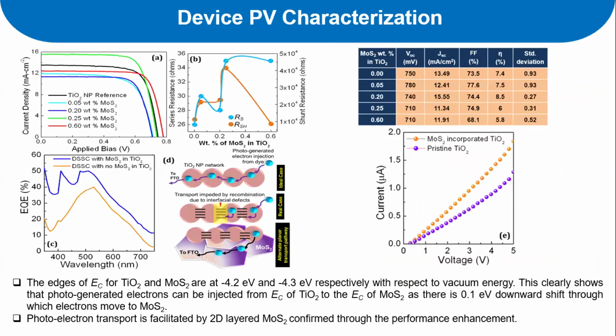Once we have that photoanode, then we go for the device fabrication, the excitonic photovoltaic device fabrication and characteristics. The first figure, A, shows the current-voltage IV characteristics obtained from the excitonic photovoltaic devices. The black curve is obtained from a device which doesn't have a 2D layer semiconductor on it, which is purely based on the organic dye molecules, which we treated as the reference device. In that particular case, the weight percentage of the moly sulfide is 0, and we have an open circuit voltage of 750 millivolts, with 13.4 milliamps per centimeter square as the short circuit current density, and 73.5 as the fill factor.